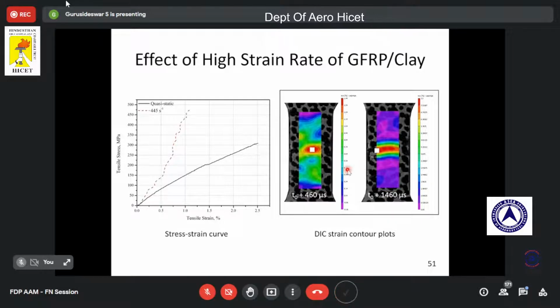And this is the DIC contour plot, just before the failure. You can see that with the help of DIC, we can have full field strain data. There is a strain localization at the middle of the sample. Further loading leads to the failure. Here you can see the failure of the sample. The sample failed at 1460 microseconds.